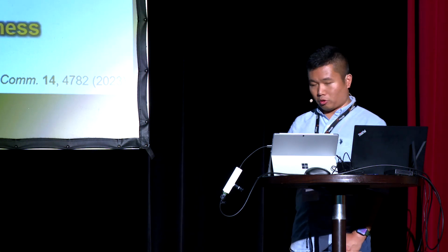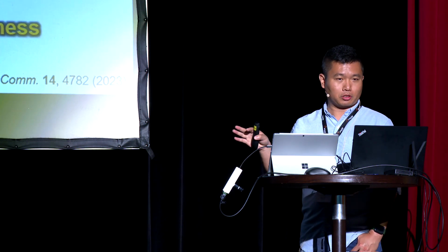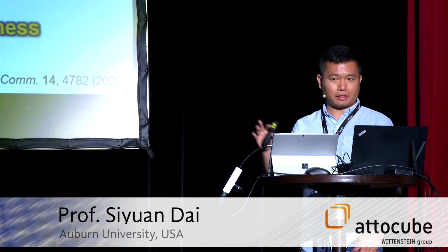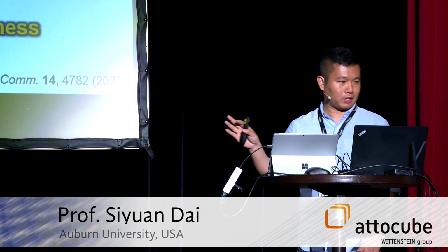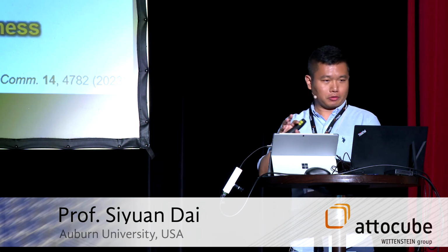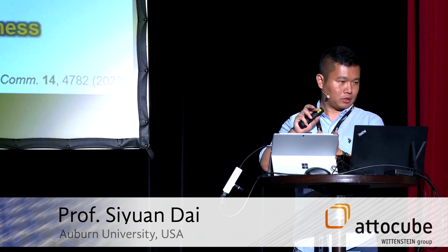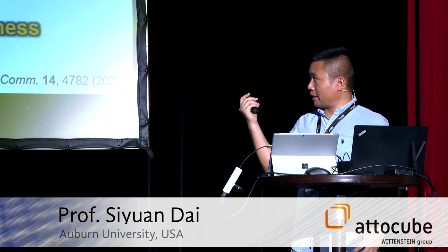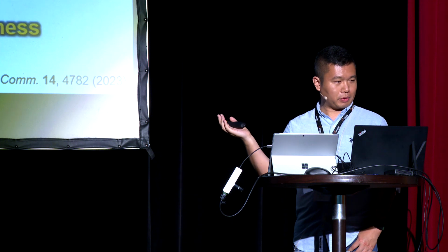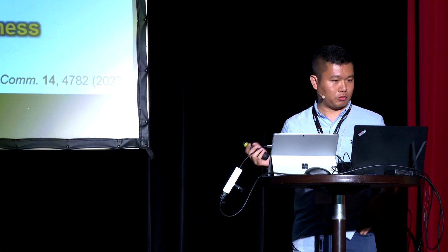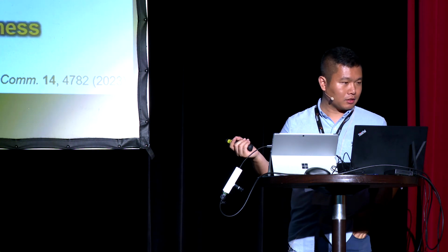Okay, so for boron nitride, the polariton in plane is still isotropic. And this twisting effect in MoO3 comes from the electromagnetic interaction between the two twisted layers. So if you are electromagnetically isotropic in plane, I won't expect too much effect if you twist them using hBN.